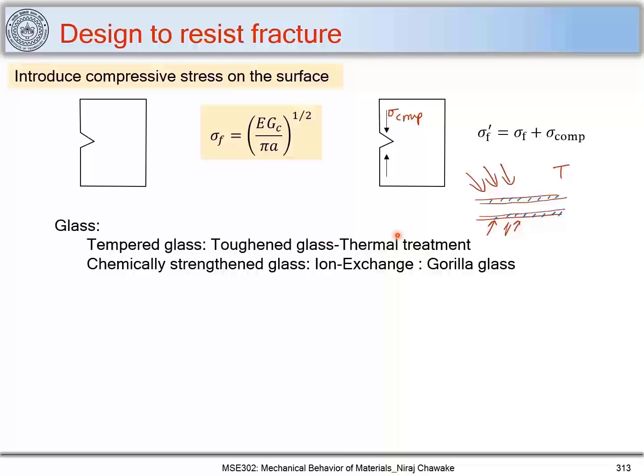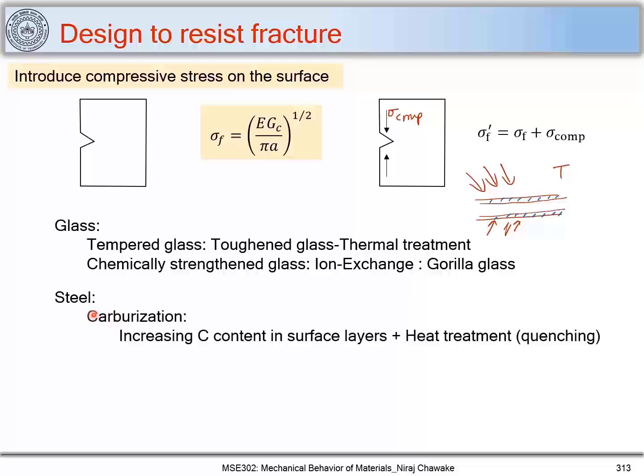That is why this is called tempered glass, which we obtain by thermal treatments. And there is another way which we can make glass tougher more effectively, that is chemically strengthened glass, which we get by using ion exchange. You can find out about this chemically strengthened glass, just use the keyword Gorilla Glass and find out how they make the surface of the glass tougher. Now in case of steel, what we do is carburization. We increase the carbon content in the surface layers and do some heat treatment such as quenching to make the surface stronger or introduce compressive stresses on the surface of steel.